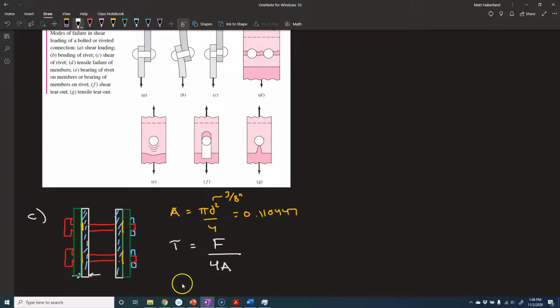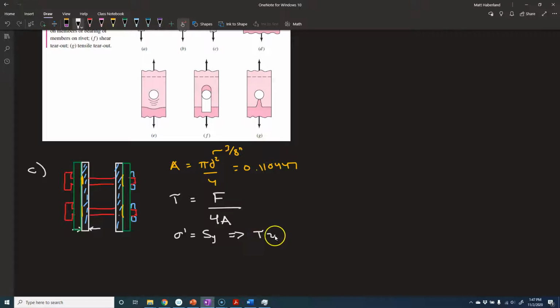And we know that our yield criterion, we're going to use von Mises. According to von Mises, the von Mises stress is equal to the yield strength when the material yields. And if you were to plug our pure shear into the formula for the von Mises stress, what you'd find is that tau times the square root of 3 is equal to SY. We did this when we talked about welding. So shear stress at yield is SY over root 3. This is about 0.577 times the yield strength. So the yield strength in shear is 0.577 times the yield strength in tension.